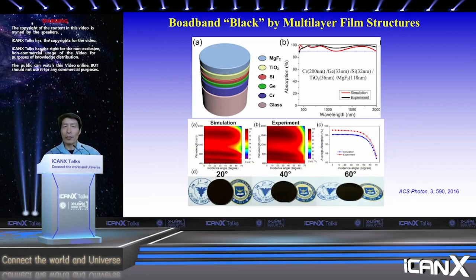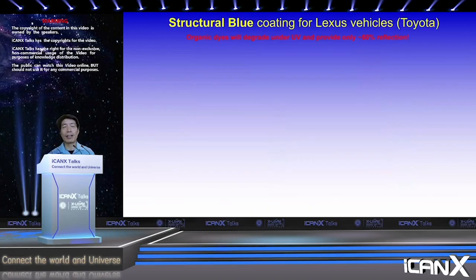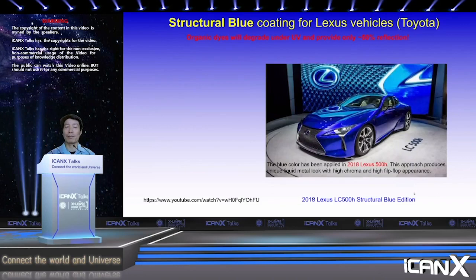The development of layer structures really got a big push from work in industry, from Toyota. They've also been developing structural colors, the so-called structural blue. Their motivation is that organic dyes degrade under UV light, and they're also not very bright because they're based on absorption, so they probably can reflect 50% of the light. Now they have developed this structural blue color, and in fact applied it on an industrial scale to the Lexus LC500, this vehicle, in 2018.